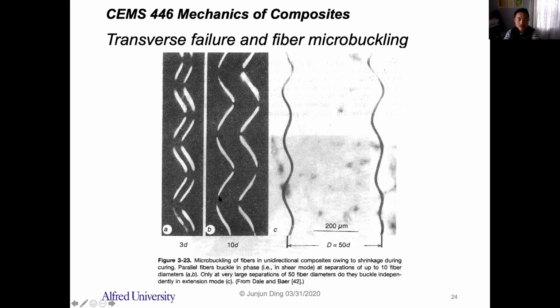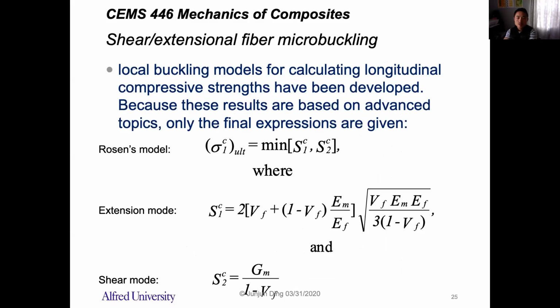So in those two cases, the buckling, the microbuckling is in the shear mode, right? That means the matrix in between will experience the shear deformation, right? Well, if this distance is really large compared to the diameter of the fiber, those microbuckling are not in phase, right? They're pretty much random. So this matrix in between will experience the extension deformation, right?